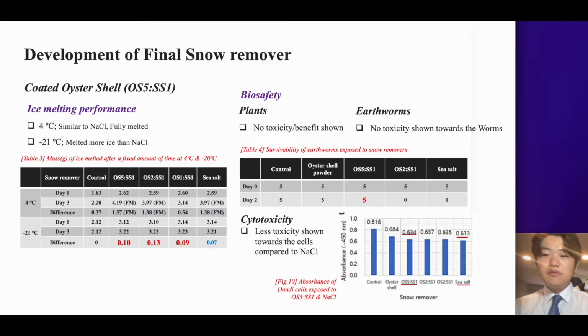For the development of oyster shells as a deicer, OS5-SS1, which is a mixture of oyster shells and sea salt in a 5:1 ratio, showed the best performance. From Table 3, it can be seen that the salt-coated oyster shells show superior performance to salt in terms of the ice melting rate, regardless of the ratio between oyster shells and sea salt.